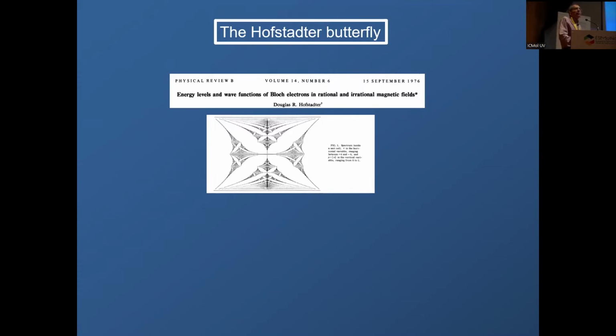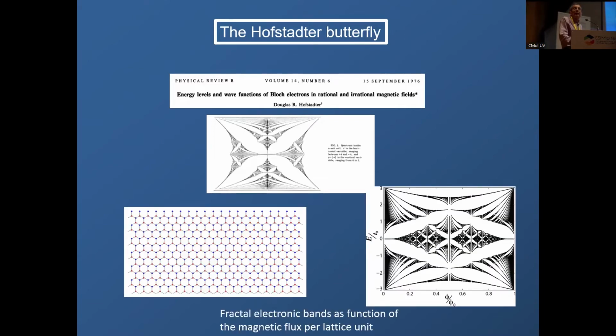And that is impossible to achieve with normal crystals because you need magnetic fields on the order of thousands of Teslas. But you can do it in a metacrystal defined by a moire like the ones I am talking to you about. These are the famous Hofstadter Butterflies, which indicate that the electronic levels in your sample build some kind of fractal pattern.